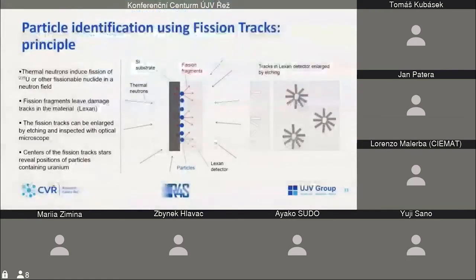And besides the particles on the substrate, we have attached a plastic detector. Concretely, it is a Lexan detector. And this detector is transparent. And we remove that detector after the irradiation. And in etching solution, we enlarge the damaged tracks inside. And those tracks are big enough to be observable by optical microscope or even by unaided eye. So once we have those tracks, we can determine the positions of the particles and continue to the next step, the analysis in the mass spectrometer.